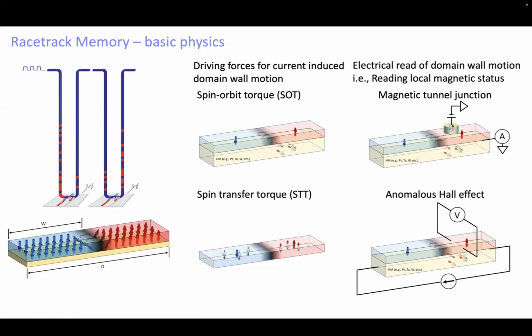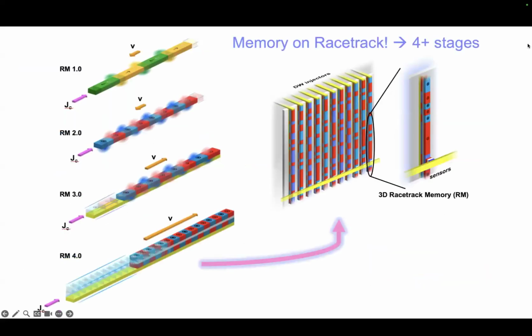Finally, we could integrate a tunnel junction directly into the racetrack. On top of the racetrack, which is a magnetic film in which the magnetization is perpendicular to the layer, we can create an insulating layer and then a counter electrode to form a tunnel junction. As you can see in this cartoon on the top right, when the domain wall moves, the magnetization under the tunnel junction changes from up to down, and the resistance through the tunnel junction will change. So if you like, this is a sort of summary of the evolution of the racetrack technology over the last 20 years.